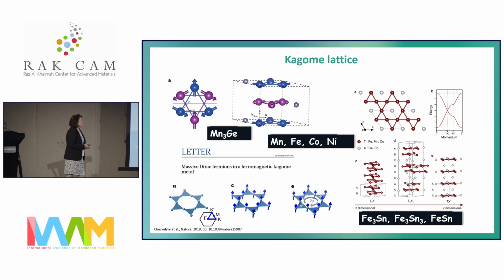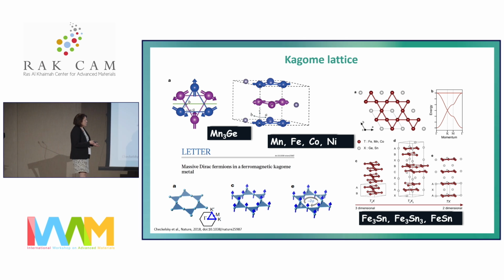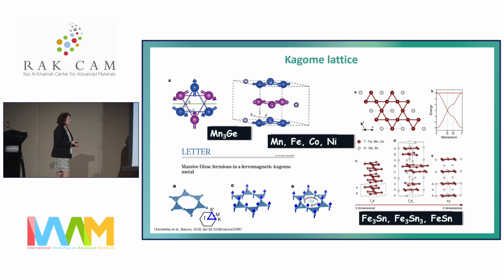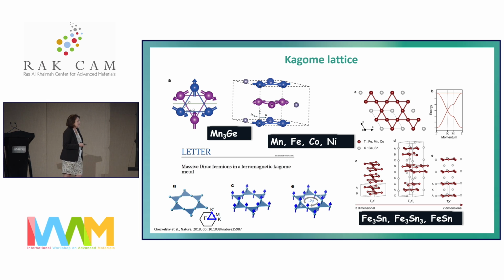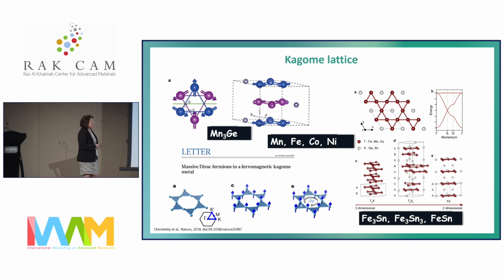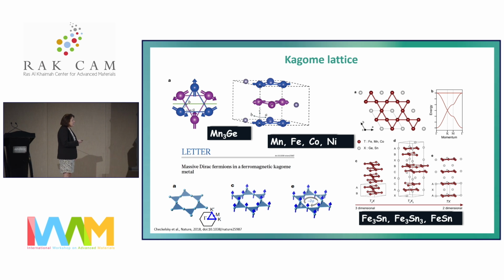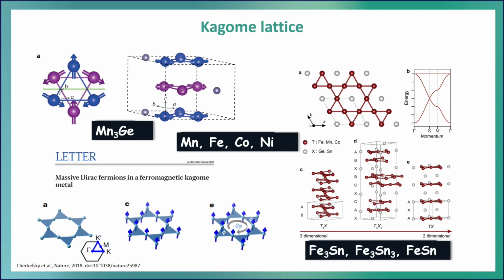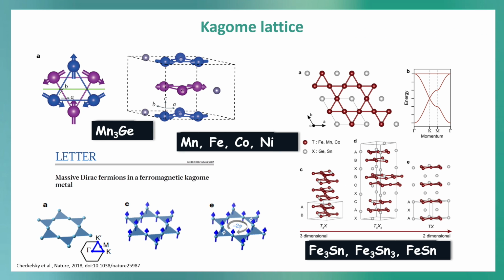Okay, so this has inspired more groups to work on the Kagome lattice in this metallic system, especially the group of Joe Checkelsky at MIT. They used mainly iron compounds. They even changed the composition to go from a three-dimensional material, like our manganese-3 germanium, to two-dimensional materials, and he found Dirac fermions in this ferromagnetic Kagome lattice, so there is now much more activity, especially because of this interesting electronic structure.